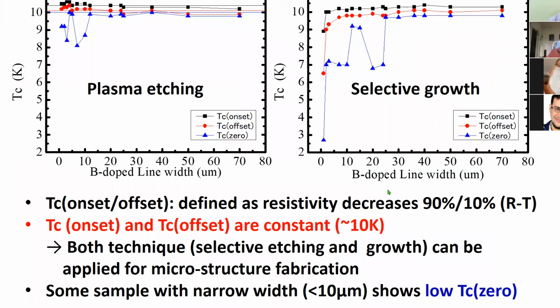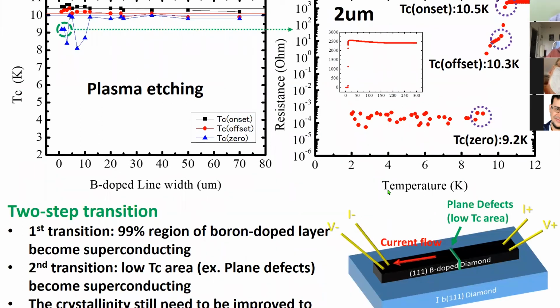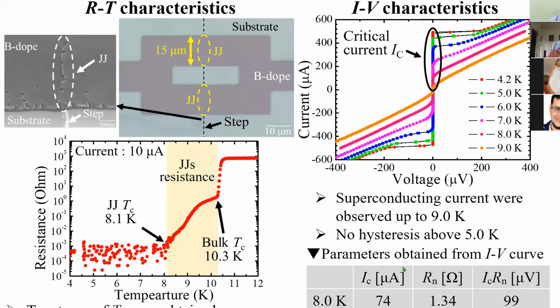So I think we need a more skillful technique to get narrow devices. We checked the line width effect on Tc. The line width means this dimension here, and with low line width we get low Tc, which may be caused by not getting homogeneous current flow, since we are making very narrow devices anyway.